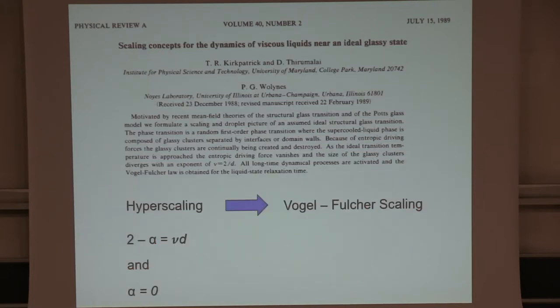As I went off the second half of my sabbatical to Japan, I continued to play with this because there seemed to be multiple lengths in this problem. The length of how thick an interface was, how big the droplets were. This seems strange, especially because, as you can see, there was almost no evidence that there were growing lengths anyway at that point, because the vote was, is there one growing length, not are there two, are there three? Well, if you believe that there's only one growing length, then you get that there's a condition of hyperscaling in the theory. And when you take the condition for hyperscaling and you say, I know that the heat capacity has a discontinuity, that corresponds to a critical exponent for heat capacity of 0, then you get a length exponent of 2 over d. So the assumption of one length hyperscaling gives you that result for nu.